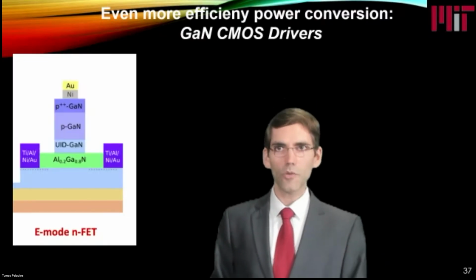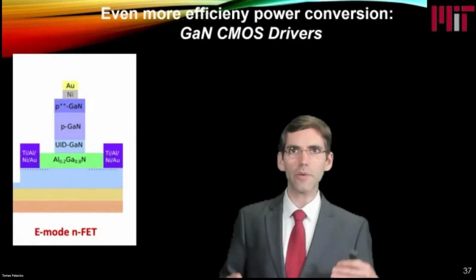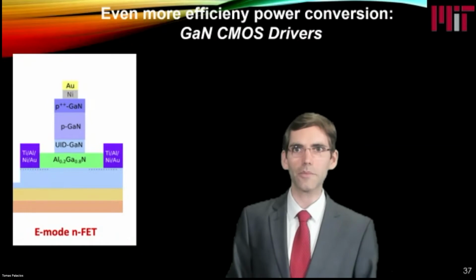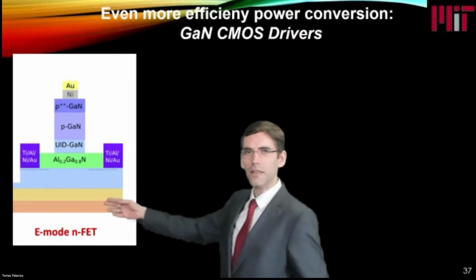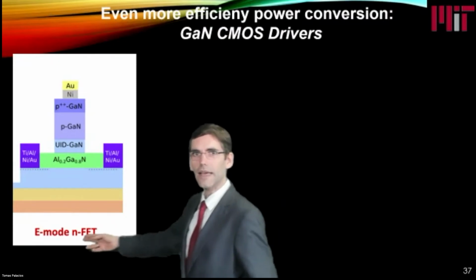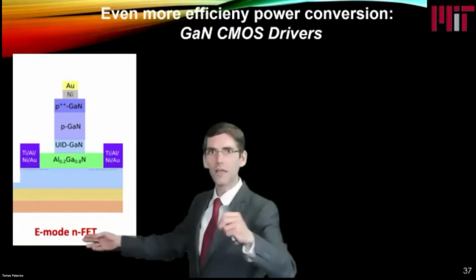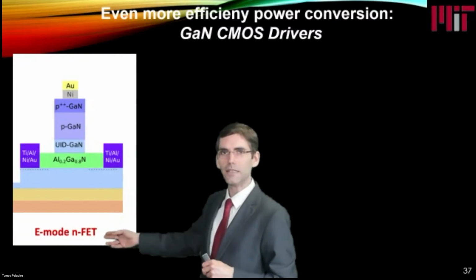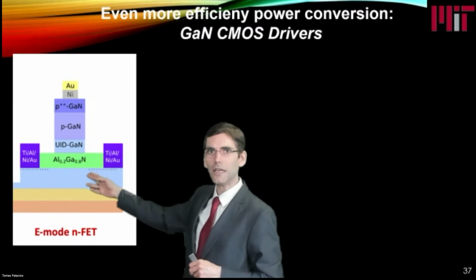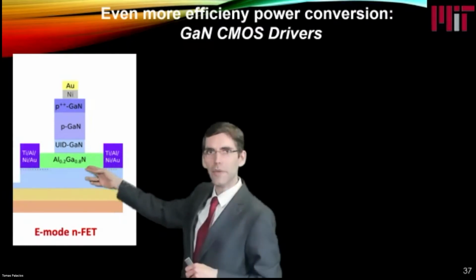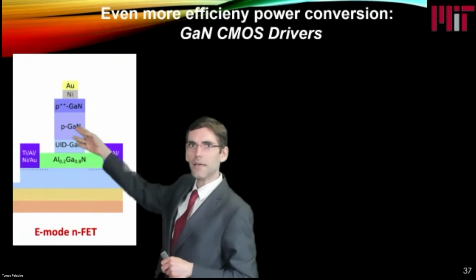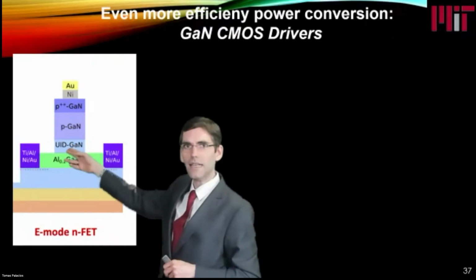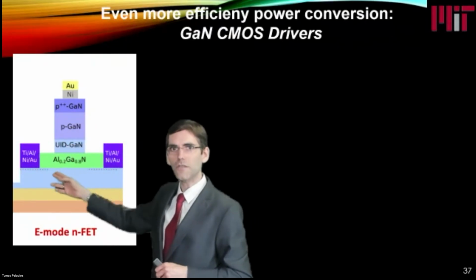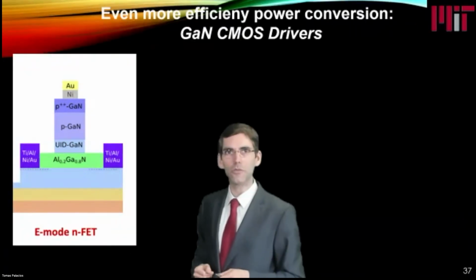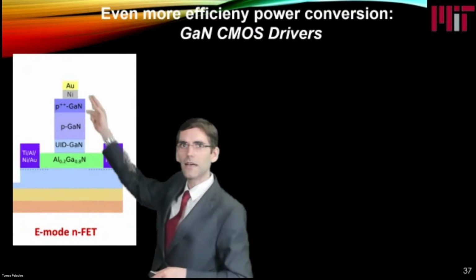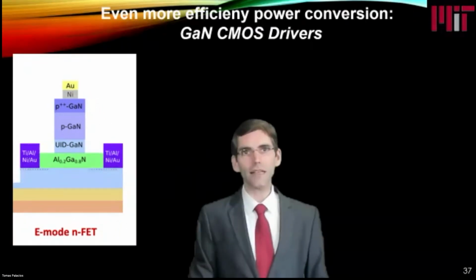So in my group, we have been working quite a lot to try to develop a true CMOS technology in gallium nitride. And for that, we started with a conventional gallium nitride enhancement mode, that is positive threshold voltage, N-type transistor, where we have a gallium nitride channel here in blue, then an aluminum gallium nitride barrier, and then a p-type layer on top, which is acting like a JFET structure to pinch off the transistor and give us a positive threshold voltage. And of course, we have the source, the drain, and the gate. This is a very well established gallium nitride transistor design.